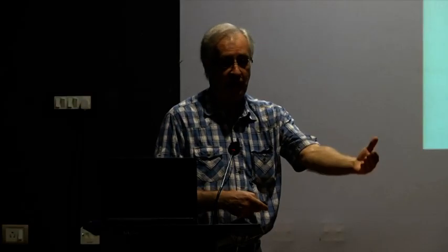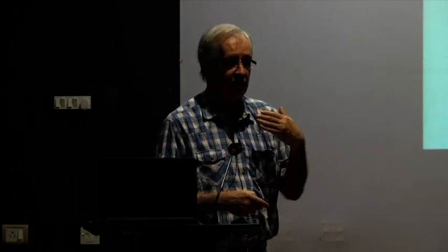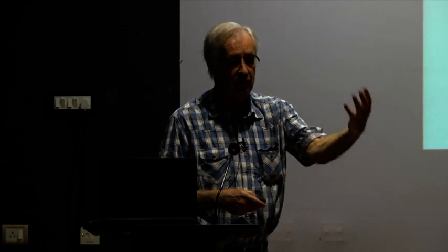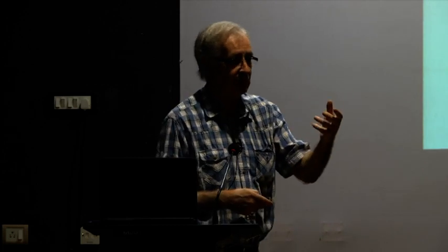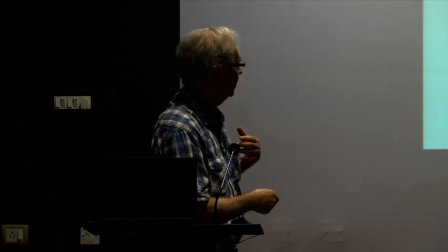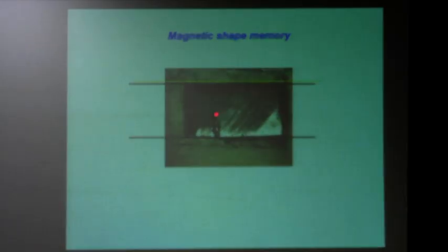You know, if you apply a magnetic field and remove the magnetic field, you're going to have a large strain, but when you remove it, it's going to remain there. So you have to rotate the magnetic field to bring it back to its old position. And this is what is happening over here.